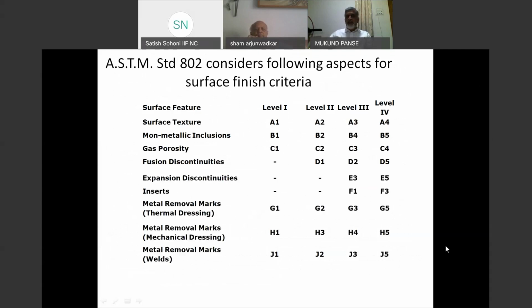Normally, the surface finish specifications like ASTM A802 or MSS SP-55 for valves specify various characteristics like surface texture, non-metallic inclusion, gas porosity, fusion, expansion, inserts, metal cutting marks, grinding marks, etc. But we are going to consider the basic surface texture of a casting. As for these other defects, there are other things that can contribute. For example, gas porosity can come because of the gas in the metal itself, gas generated by the molding material, gas picked up during pouring in the running system, etc. So we'll concentrate basically on the basic texture of the casting and how we should get a good texture.